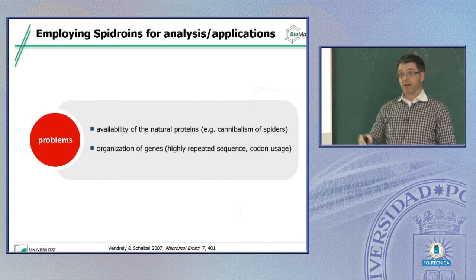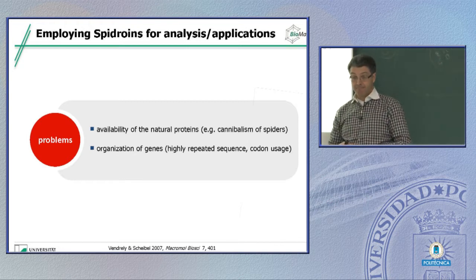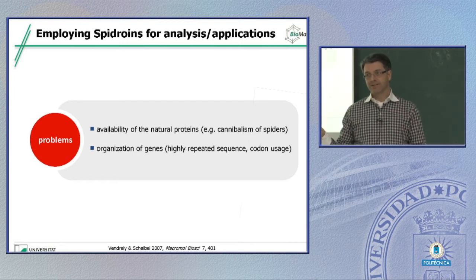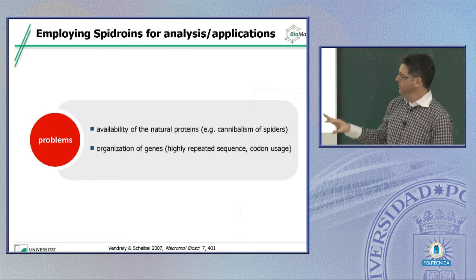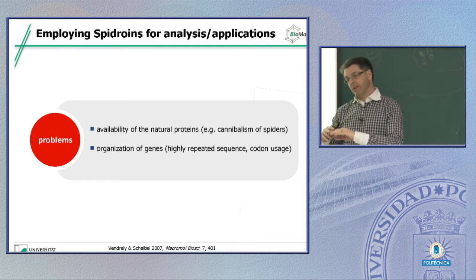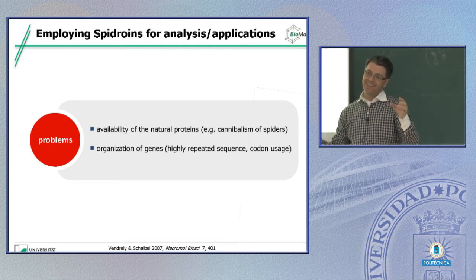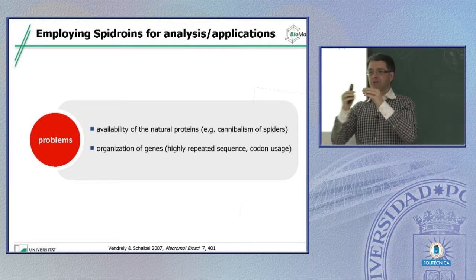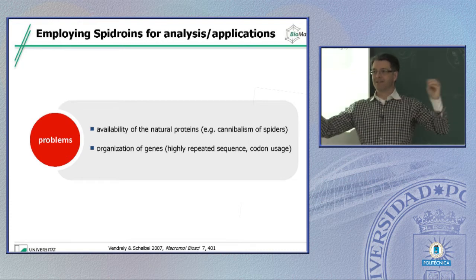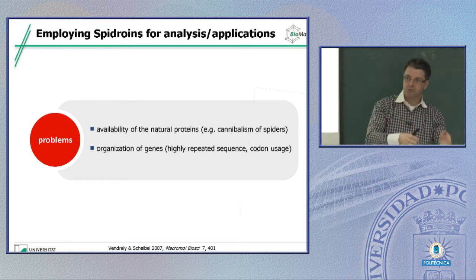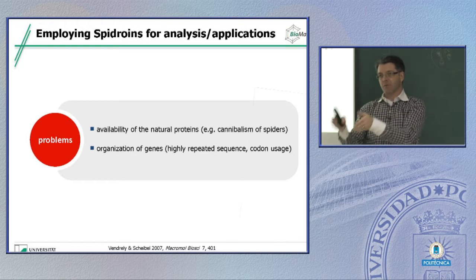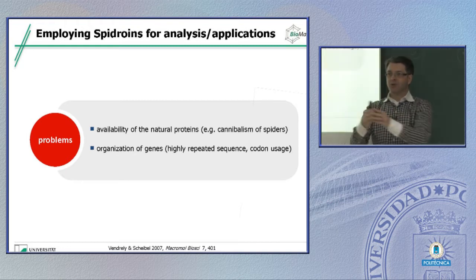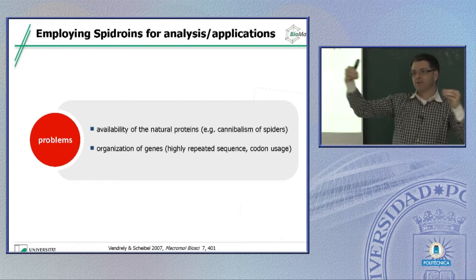And you might have heard about the goats that make silk in milk, which technically works, but practically fails because in milk you have a lot of other proteins like caseins, and caseins are proteins pretty similar to silk proteins. They're intrinsically unfolded, they behave like silk proteins, and if you try to remove caseins from silk proteins, you fail. They will also co-purify. So what you then have finally is a silk milk fiber, so to say.